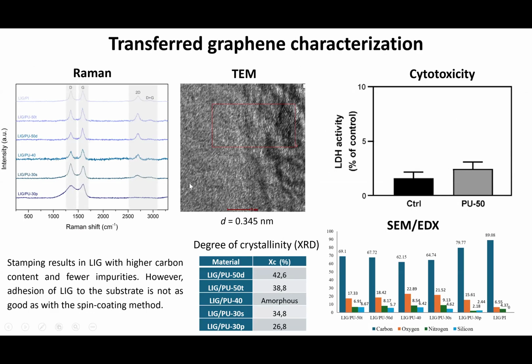Here is a bit of characterization of the graphene made on these polyurethane materials. TEM again confirms lattice spacing, indicating graphene. We actually, for this one, performed cytotoxicity tests, and we showed that the material is non-toxic. And it's highly crystalline. And then we also did EDX and SEM. You see that all the materials have high carbon content, but they all contain also a certain degree of oxygen. So there's a bit of graphene oxide there. And I think this is the case with most LIG that you will make.